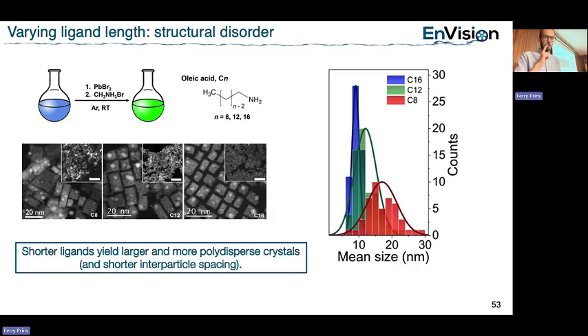So we can do some analysis here. We know these are all excitons, independent of size - we do this analysis, straight line with PL, so we know they're excitons. What's important for us is the distance between the particles, the center-to-center distance, because that's where the dipoles are. It's not so much the distance between two particles, which would matter for electron transfer - it's the distance between the dipoles. So we do the size analysis, and you can see that C8 gives a very broad polydisperse ensemble with relatively large size, whereas C16 gives a sharper distribution, more monodisperse, smaller size.